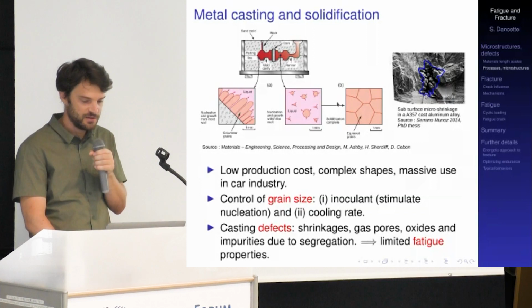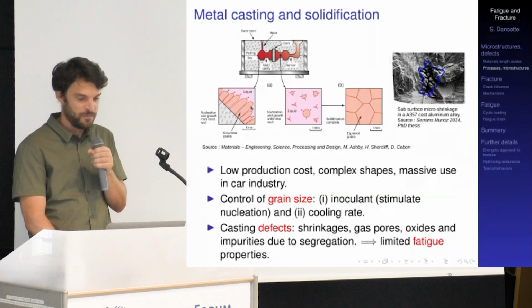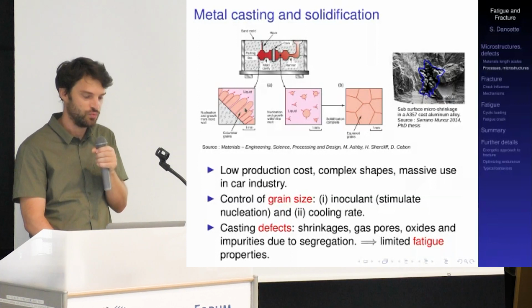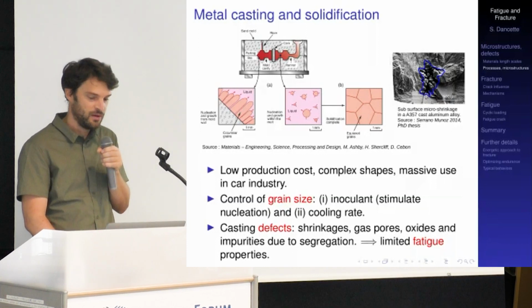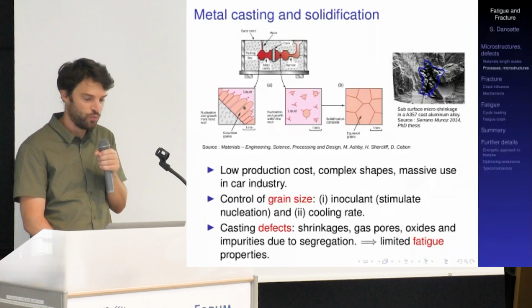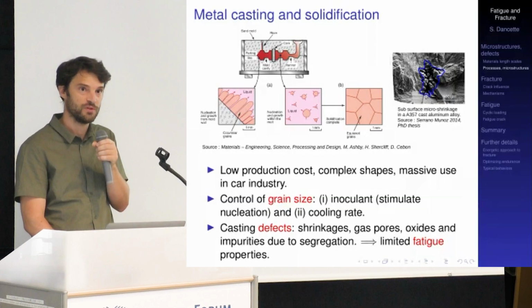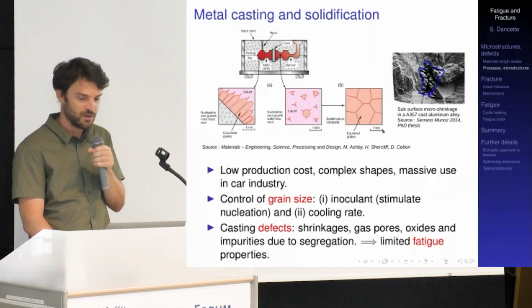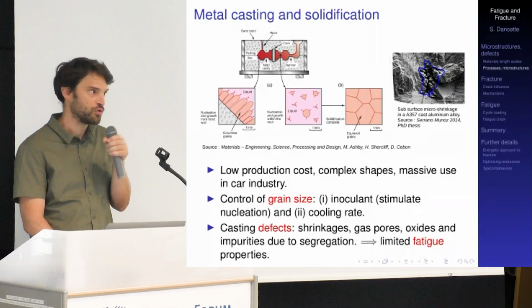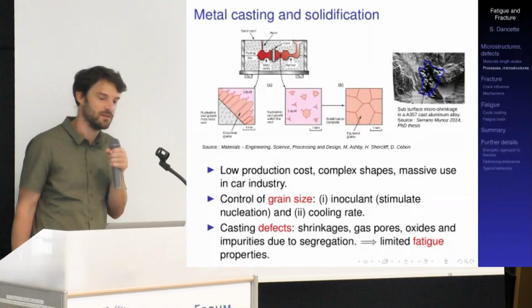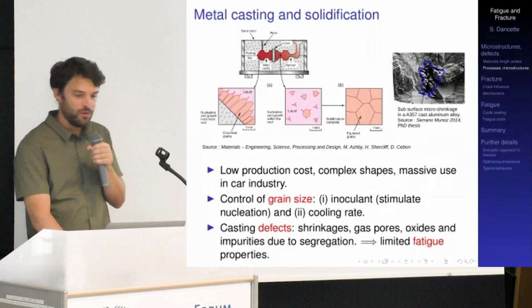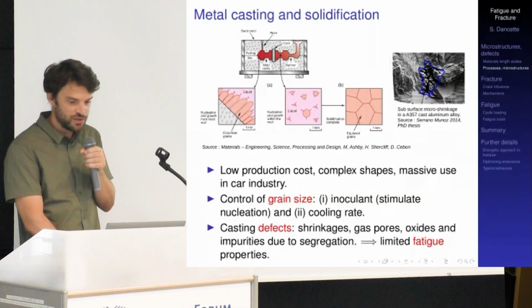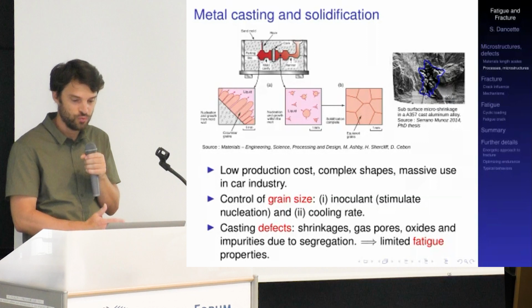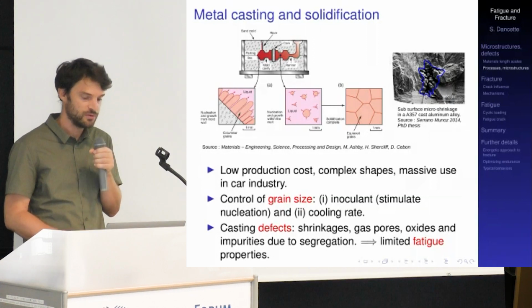But the important thing here is this. In fact, depending on how the liquid will solidify into some solid material, then there may be a whole range of defects that can occur during the solidification process. And one example is this kind of micro shrinkage that can occur during the solidification. You can see that these micro shrinkage defects can be as huge as several hundreds of micrometers.